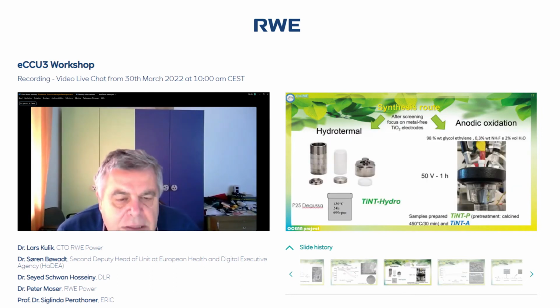What is important is that this is something unique, because normally you don't consider an oxide like titanium oxide to be a good hydrogenation or electrocatalytic hydrogenation catalyst. Normally you consider metals, but the typical problem with all metals is that oxalic acid is a strong complexing agent, so it dissolves them, and you don't obtain very good stability in most practical systems. This is the reason why we arrived at this system as the best. Next slide, number 17.